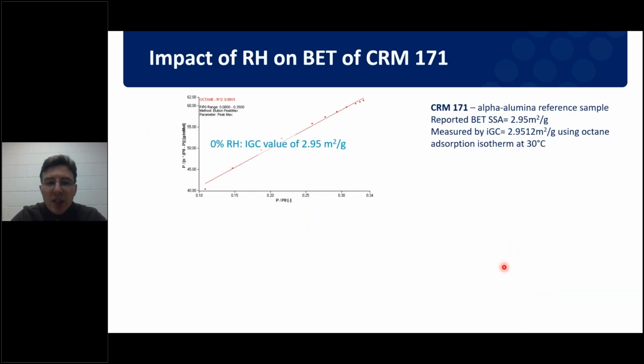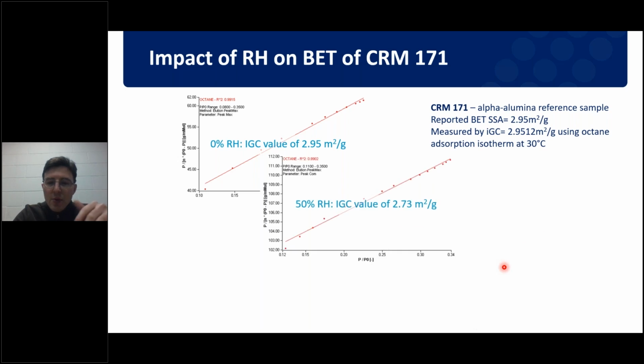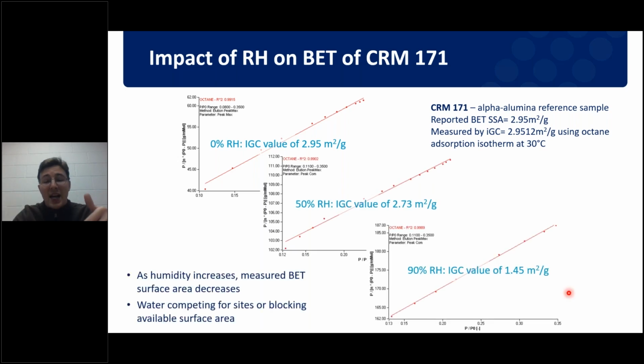On this next slide, we can look at the influence humidity can have on surface area. Now we're looking at a similar material. Once again, this is a CRM sample. This is 171, so slightly higher surface area. And this is a sample of alumina, so we're only going to be exhibiting surface site adsorption. And here we can see the really large impact that humidity has on surface area. As I go from a dry column to one with 50% humidity, to one with 90% humidity, the effect humidity has on surface area is drastic. At 50% RH, we're getting a small reduction in surface area. When we get to 90% humidity, this becomes much more pronounced, and we have nearly halved the surface area of our sample.